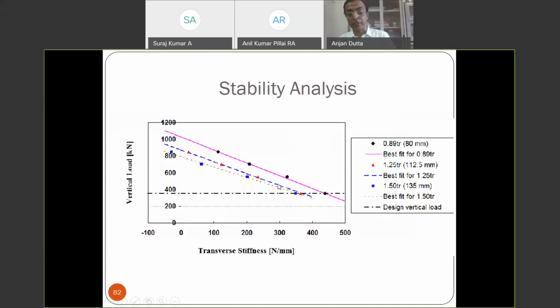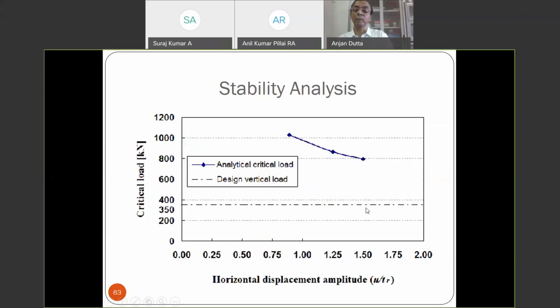But before you go ahead, you should also check the stability, and you can see we have played with the displacement level. 0.89 TR, where TR means the total thickness of the rubber layer, and 1.5 TR, because we don't have any Indian code, so we follow the American code, and they say that you have to test up to 1.5 TR. All these points are much higher, so this is my design load line and this is my stability. It is highly stable under the vertical load, no issue.